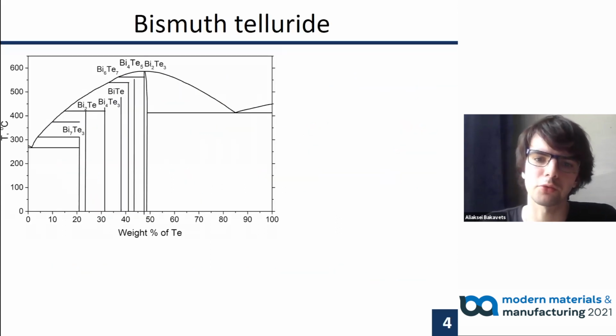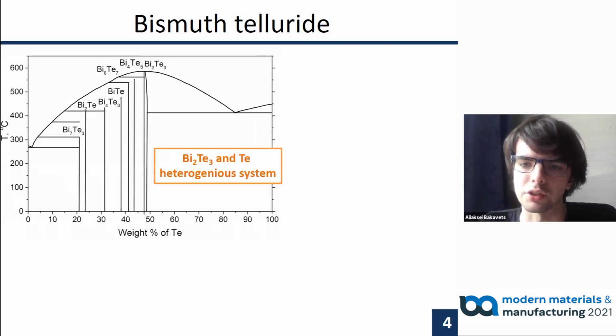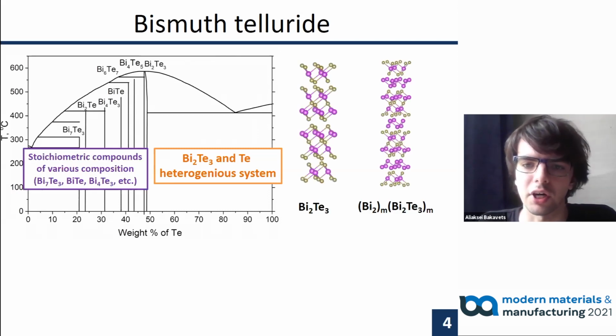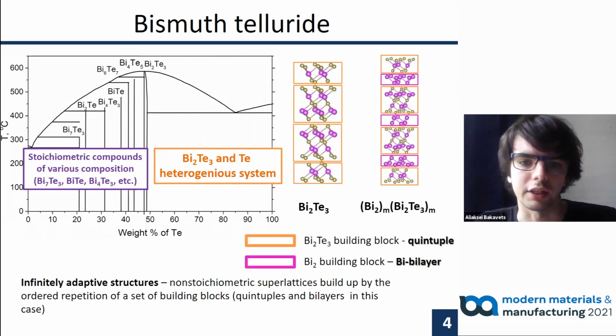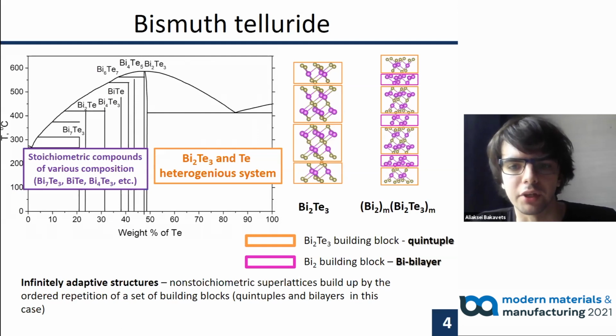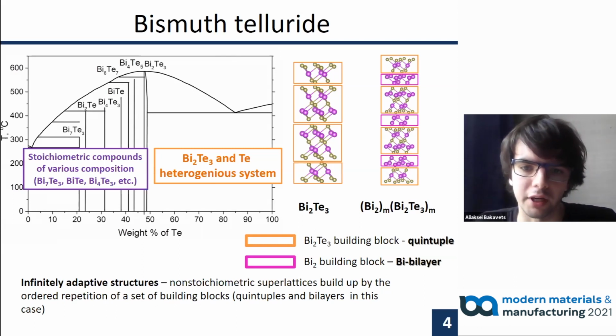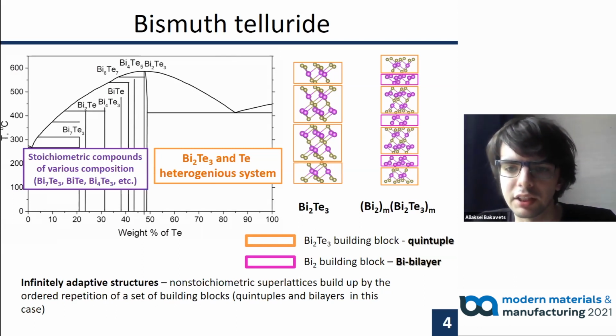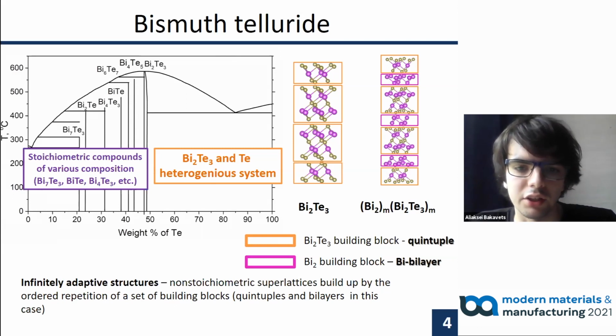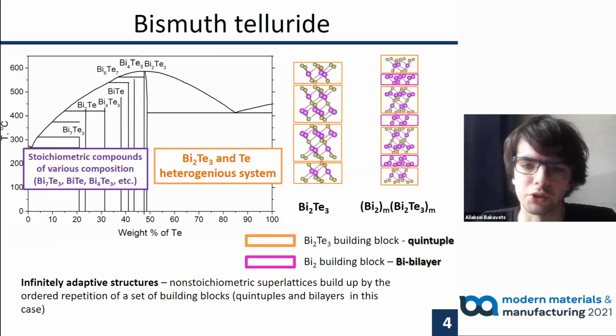According to the phase diagram of the bismuth-tellurium binary system, a heterogeneous system is formed at high tellurium content, whereas high bismuth content favors formation of a variety of stoichiometric compounds like Bi2Te3, Bi4Te3, Bi2Te, etc. A 5-atomic layer Bi2Te3 quintuple can be combined with a 2-atomic layer of bismuth, a bismuth bilayer. In literature, structures formed by combining these two types of building blocks are designated as infinitely adaptive structures. The infinitely adaptive series is not limited to stoichiometric compounds. In fact, any composition between these two lines on the phase diagram is possible.